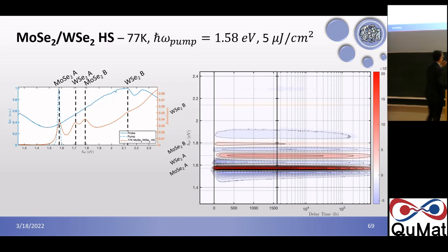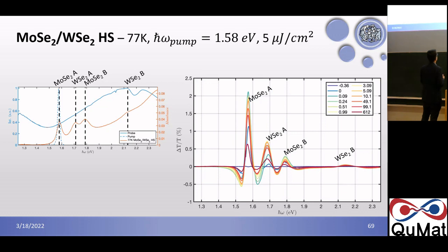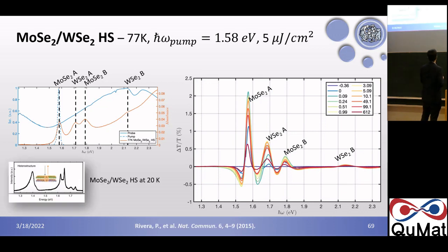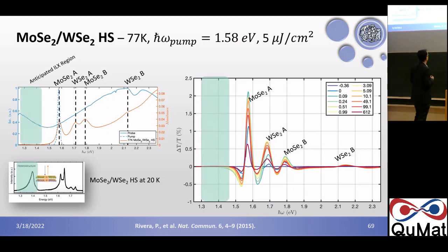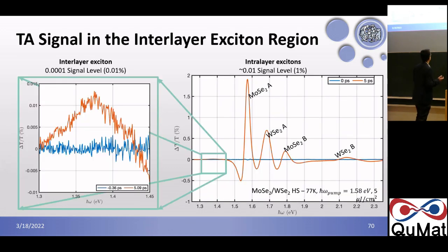And this is exactly what I've shown before. The interlayer charge transfer takes a couple of 100 femtoseconds. And this is very clearly seen. But now what we can do is look at the luminescence of this heterostructure. The interlayer exciton is emitting in this range between 1.3 and 1.5 electron volts. Here, if we look at our signal, we see almost nothing. But since we have a very high signal to noise, if we zoom in, it is not really zero. There is a very weak but clear positive signal. So this is really the signal of the interlayer exciton.